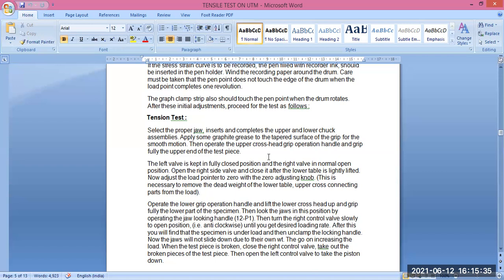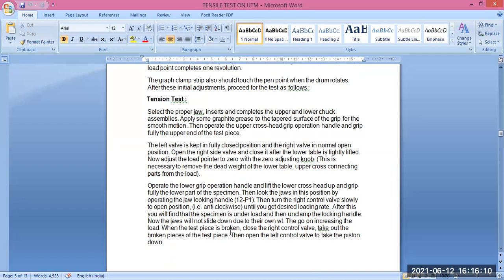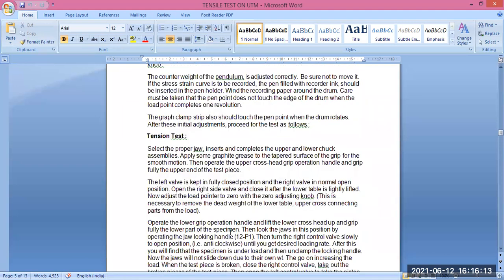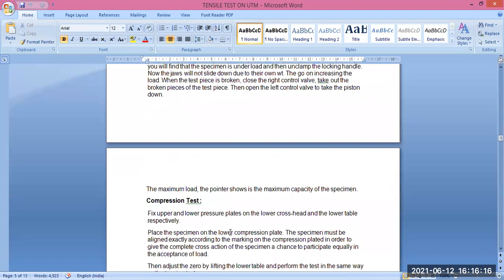Then turn the right control valve slowly to the open position, that is anti-clockwise, until you get the desired loading rate. After this, you will find the specimen under load, and then unclamp the locking handle. Now the jaws will not slide down due to their own weight. Then go on increasing the load. When the test piece is broken, close the right control valve and take out the broken pieces of the test piece. Then open the left control valve to bring the table down again. The maximum load pointer shows you the maximum capacity of the specimen itself.